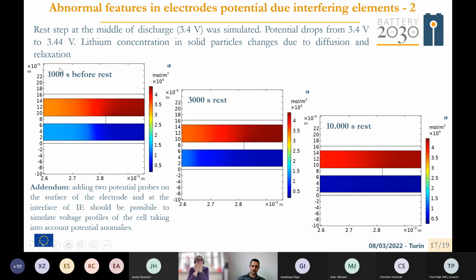As you can see in the progression of the plots, from the first plot that accounts for the situation of lithium distribution before rest, and the second two that account for the situation after rest at different times, you can see in the color the relaxation of distribution of lithium in solid phase over time.